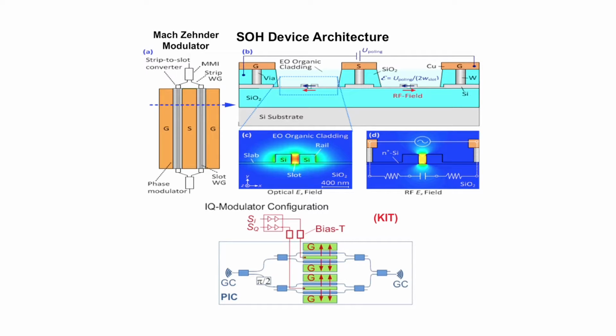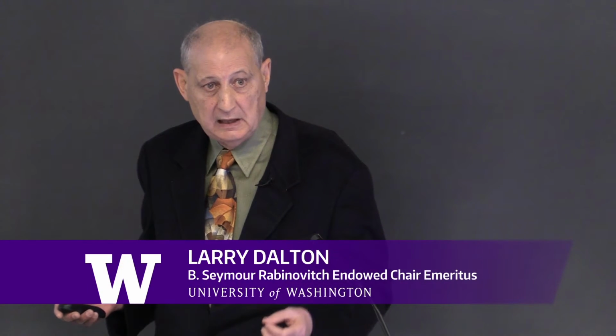This device has a V pi L that's roughly a factor of 10 worse than our best devices. But the point I would particularly like you to note is that this structure concentrates both the optical field and the RF electric field in these nanometer slot regions. And that leads to a dramatic enhancement of the optical nonlinearity. Remember, optical nonlinearity is going to be determined by the strength of the electric field you apply and the ease at which your charge distribution is perturbed.